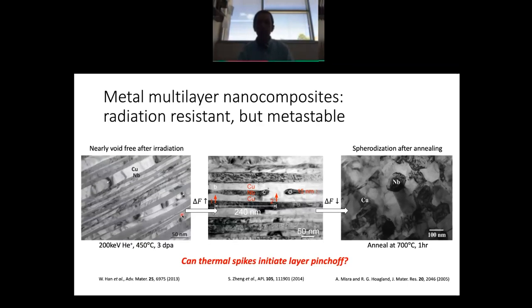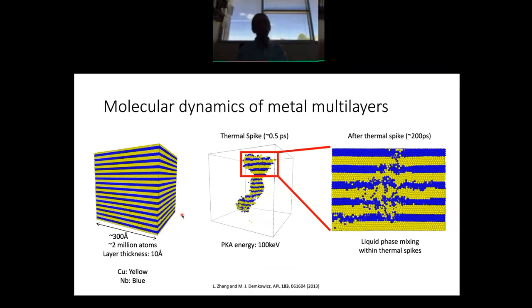So we studied this again using molecular dynamics. Here's an example of a model that we use. This particular model has about 2 million atoms. It's about 30 nanometers on the side. So in this particular picture, the copper atoms are yellow, the niobium atoms are blue. We put in a primary knock-on atom that had 100 kiloelectron volts, and we got this oddly shaped thermal spike.